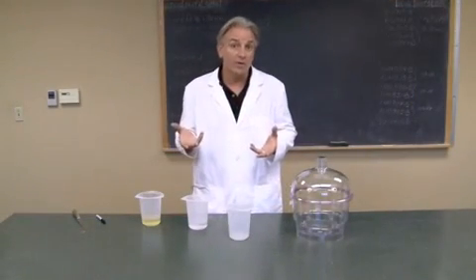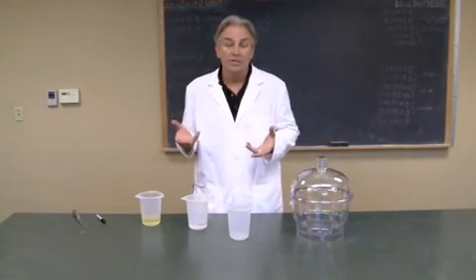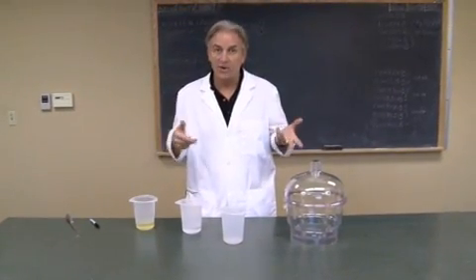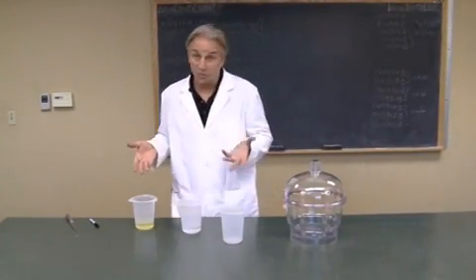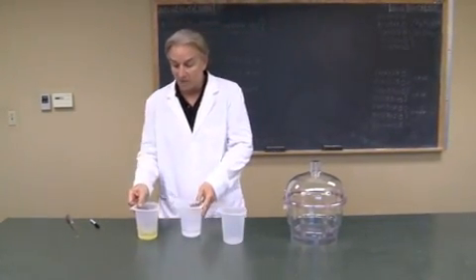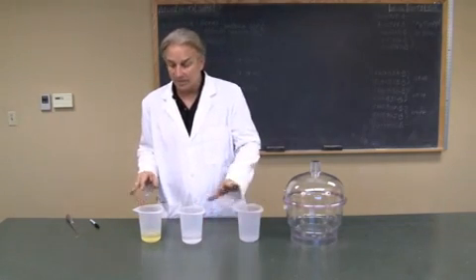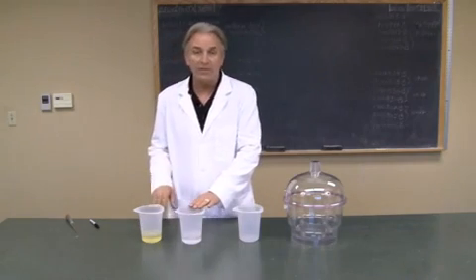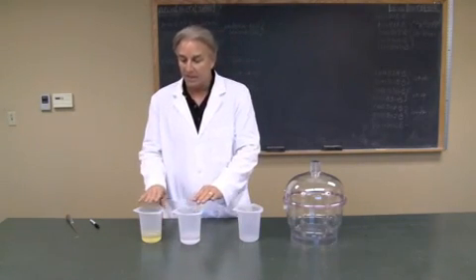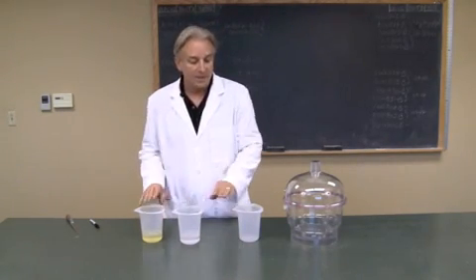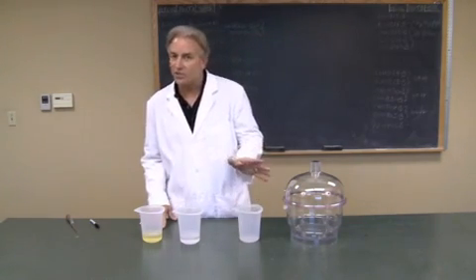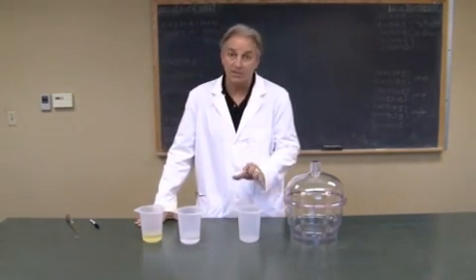It's very important that you refer to the technical data sheets for the correct ratio, either by volume or by weight, to get the correct measurement. In this case, it's one-to-one. So we've measured out equal volumes in plastic containers, beakers. In this case, we're going to do 150 milliliters of Part A and 150 milliliters of Part B, and then mix them and pour them into a secondary cup. This ensures that we don't have any sticky spots or unmixed material.